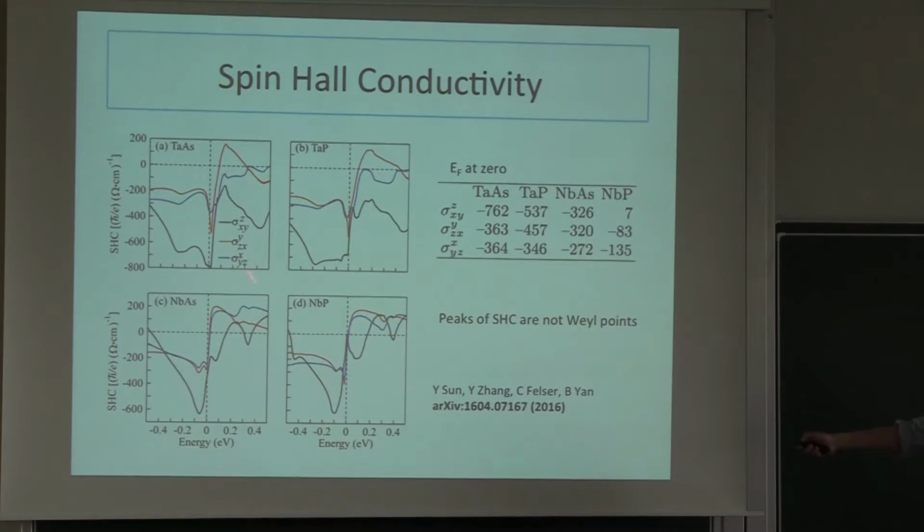And well, here, this is the energy dependence. Where the Fermi energy is, whether it's in the band crossing gap or crossing some other bands, it really matters. And here you see some peak values. This gives us a direction, in what kind of direction to dope the material to manipulate it. We may optimize the spin Hall effect.